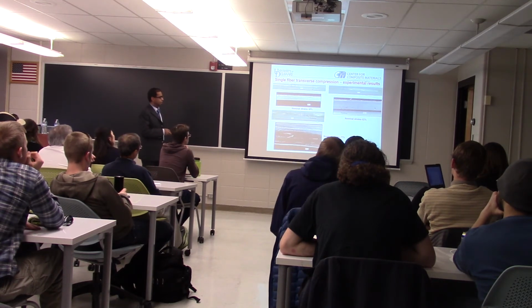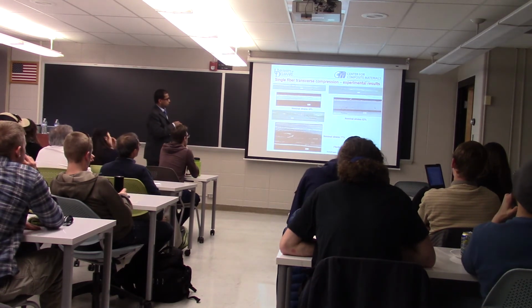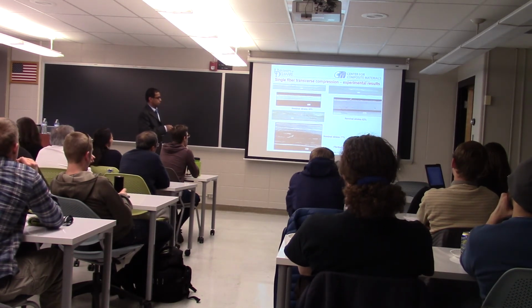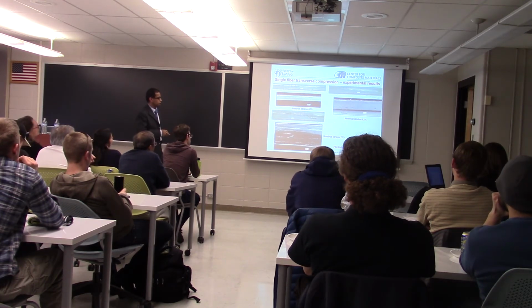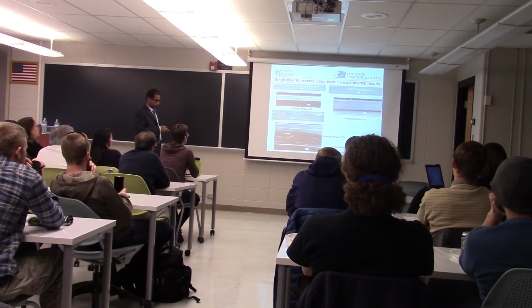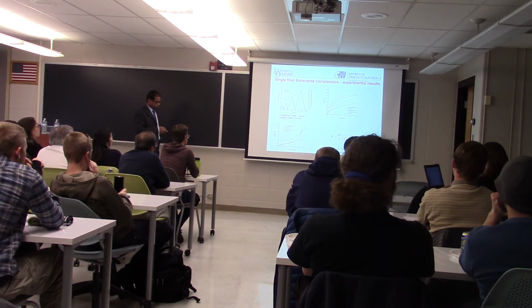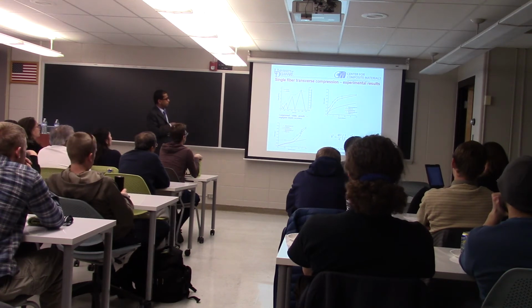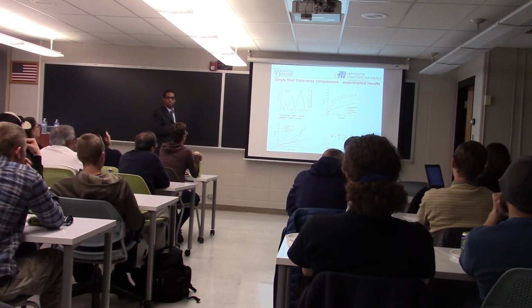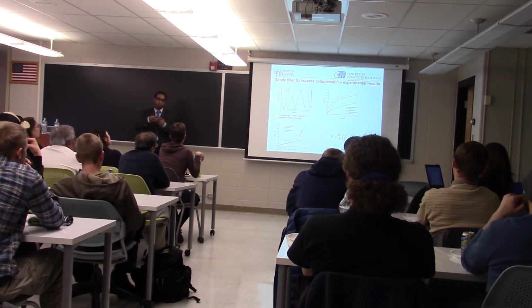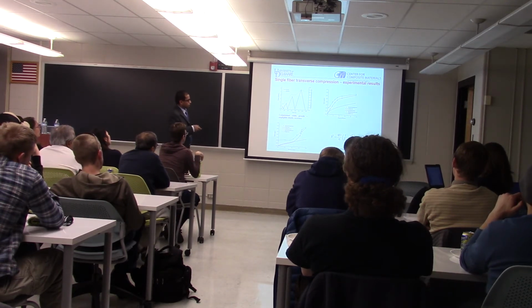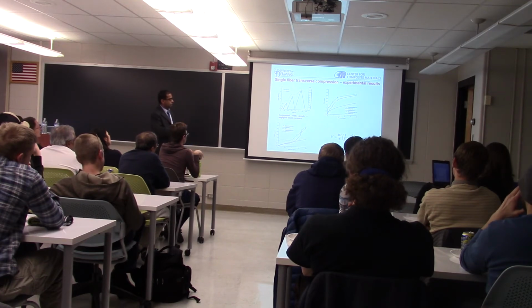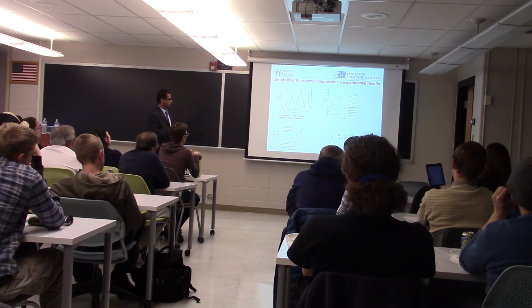So here are some microscopy images of the compressed fibers at different strain levels. Here the fibers are loaded uniformly along the length, and we see fibrillation at the surface of the fiber for strains greater than about 40%. For higher strains, we see significant splitting of the fiber along its length. And the in situ compressed width data shows that there is negligible elastic recovery. So once the fiber grows, it doesn't come back. And the compressed width also plateaus at higher load levels to approximately 3 fiber diameters.